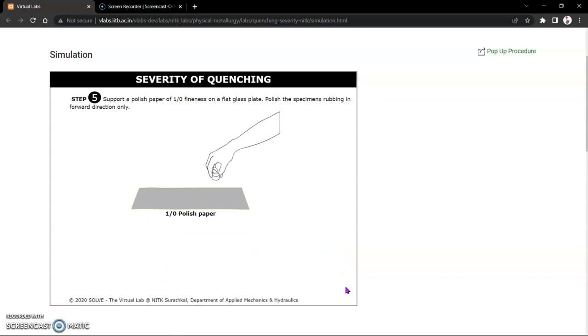After that, step 5. Support a polishing paper of 1/0 fineness on a flat glass plate. Polish the specimens, rubbing in the forward direction only.